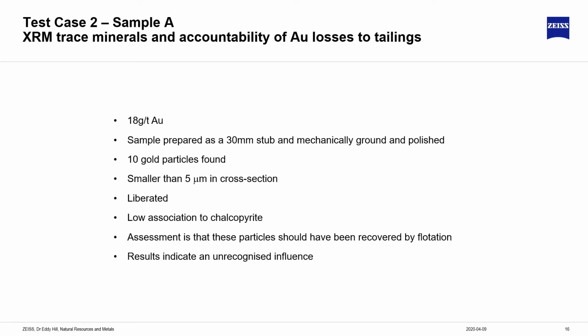The ore itself reports for sample A at 18 grams per ton gold. The sample was prepared as a 30 millimeter stub and mechanically ground and polished, and this proved significant. 10 gold particles were found, by which we assume that the analysis is statistically viable. These were smaller than 5 microns in cross-section. They were liberated. We encountered low association to chalcopyrite. And the assessment is that these particles should have been recovered by flotation. However, many of these particles reported to the tailings. So the results indicate an unrecognized influence.